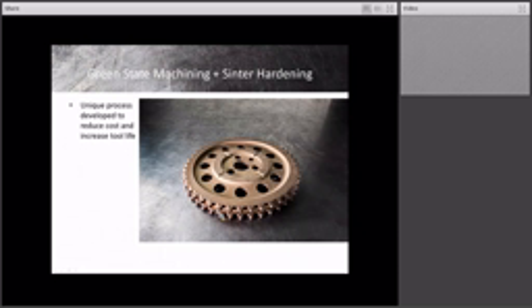So you've taken a part that's been machined, a groove cut between teeth so it can have multiple chains run on it, and at the same time it's been machined in the green state, which causes much longer tool life and generally lower cost. It adds an operation for curing because that's necessary in order to make the powder stick together effectively for the machining, but that's not a high-cost operation, and generally it runs a little cheaper than solid-state machining.